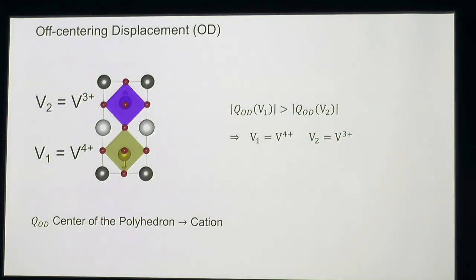The other lattice distortion is called off-centering displacement, which can be quantified by the distance between the center of a polyhedron and the position of the vanadium. Generally speaking, vanadium 4+ has a larger displacement, also because of the ionic size effect. Because in the perovskite structure, the smaller the B-site ion is, the larger the displacement is.